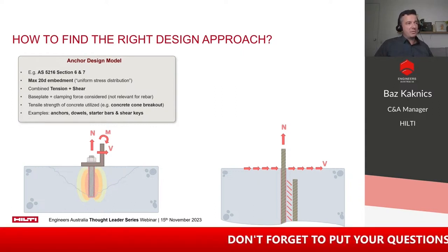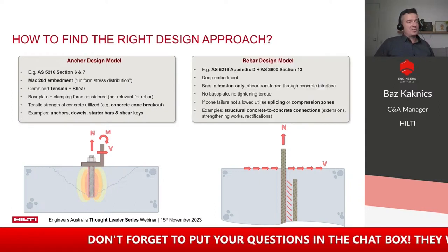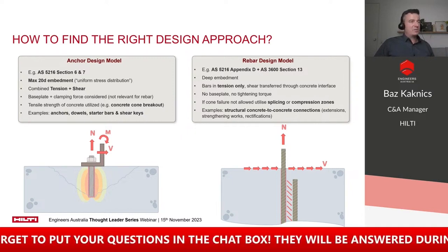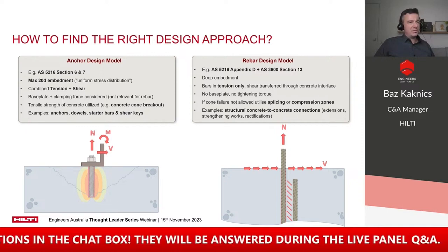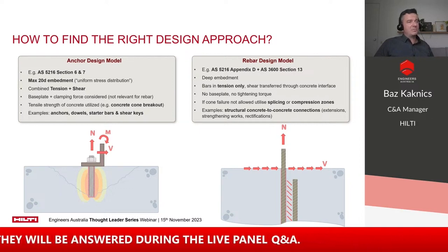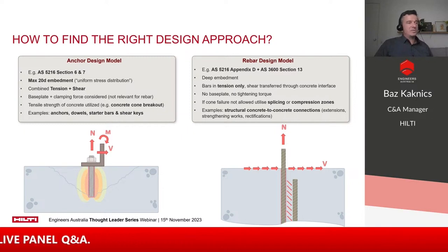must be accounted for. For the more traditional applications of post-installed rebar, however, the specifically developed rebar design methods should be utilized. These are suitable and safe to be used for deeper embedment depth, but the bars must only take tension forces, and the shear force must be transferred by different ways, for example, by roughening the concrete interface.